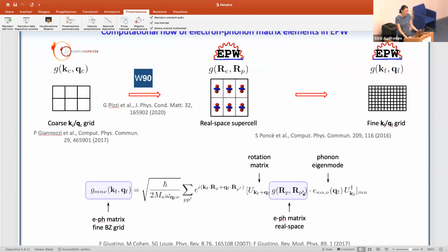And I would say the strength of EPW is that it couples density functional perturbation theory with maximally localized Wannier functions. So this allows accurate calculation of electron-phonon interactions. In other words, electron-phonon matrix elements, starting from coarse grids calculated with Quantum ESPRESSO, then using the Wannier interpolation technique by calling the Wannier90 code as a library, and then obtaining the electron-phonon matrix elements in real space. And then you can go back to the fine mesh, basically using any mesh that you can afford.